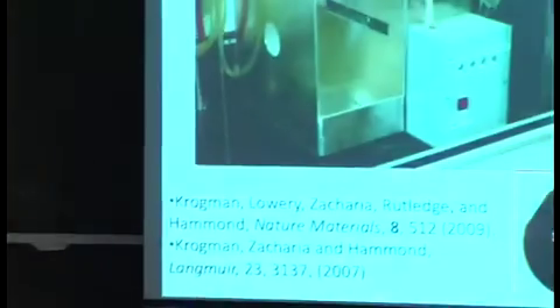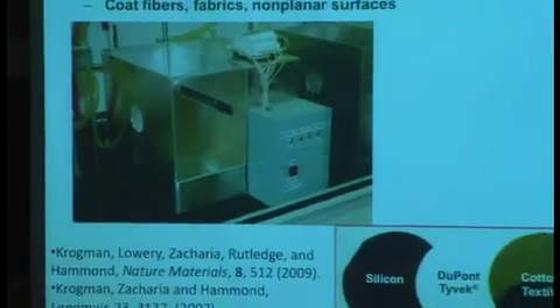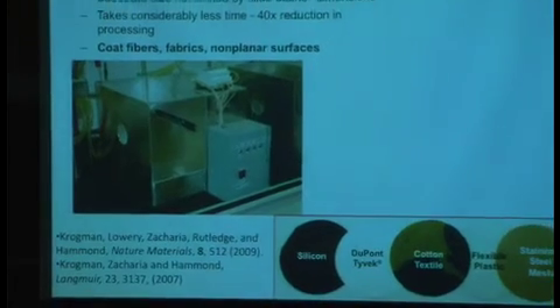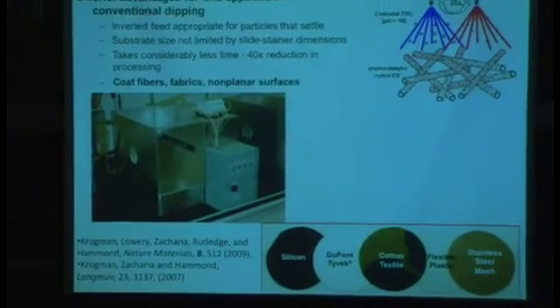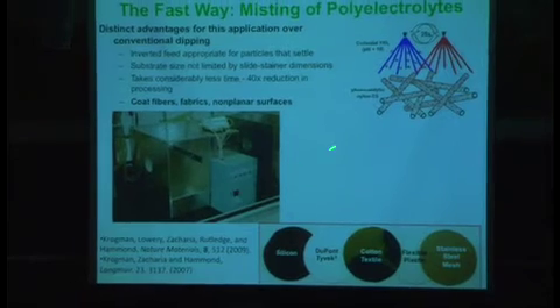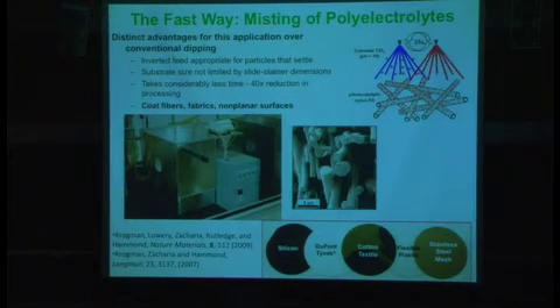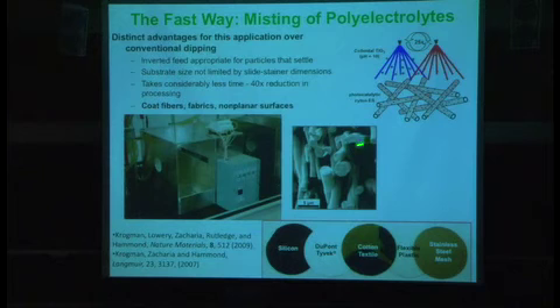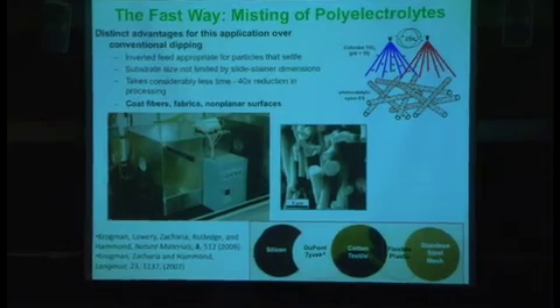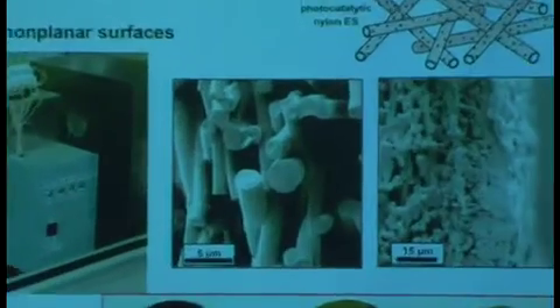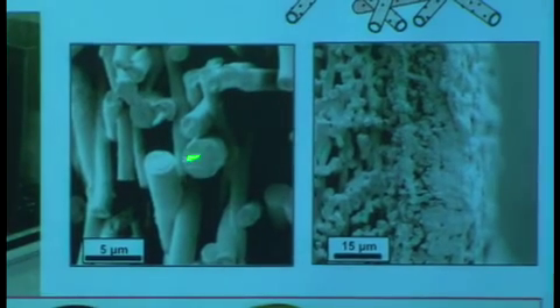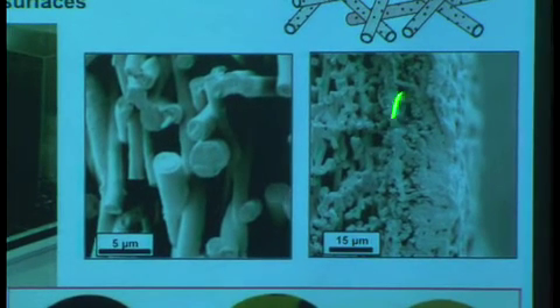We've adapted this. My student has gone on to start a company based on this spray layer-by-layer technique because it can be used for a very broad range of applications. In our own work, we've used this to coat both flat and porous substrates. And this gives you an idea of an electrospun fabric from Greg Rutledge's lab, which we coated with a nanoscale thin coating. We can actually get each of these fibers individually coated, which gives us a great deal of flexibility. And we can ultimately get these films to bridge across and create a uniform film.